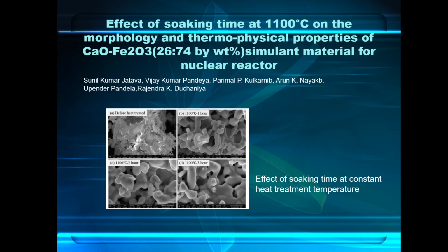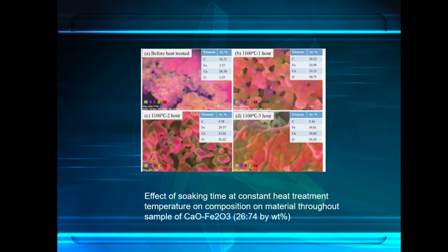The porosity of material is higher at 1100 Celsius for 1 hour soaking time, but it decreased with increasing soaking time at the same heat treatment temperature. Because of agglomeration, the agglomerated particles in the material increased with increased soaking time at constant HTT. This happened due to formation of new phase at higher temperature. And the next one is the effects of soaking time and constant heat treatment temperature on composition of material throughout the sample.